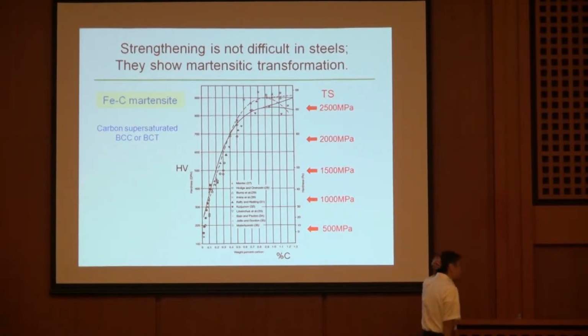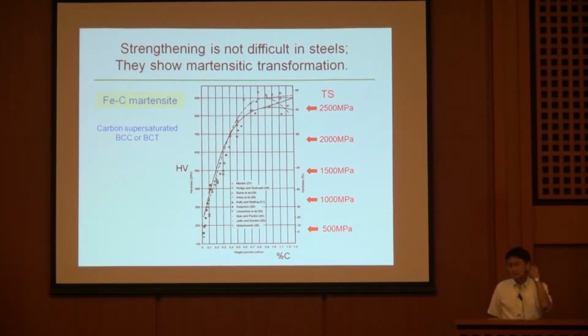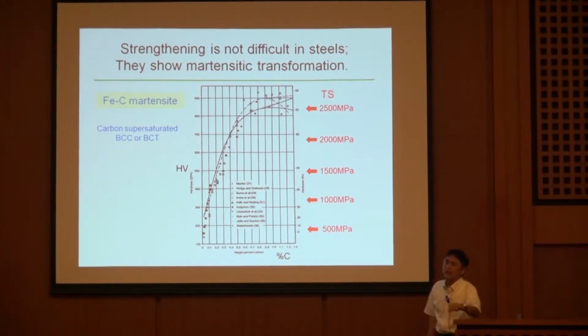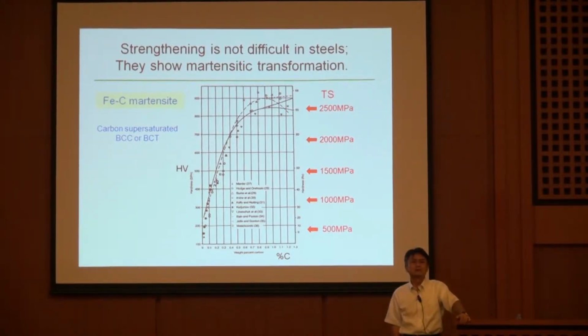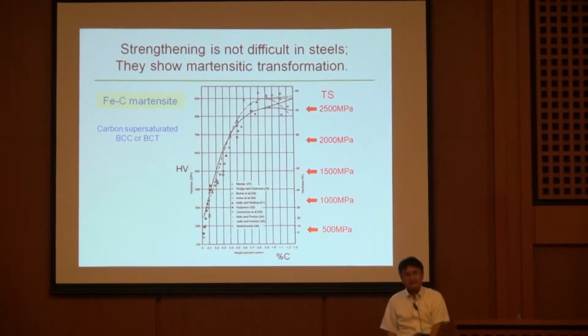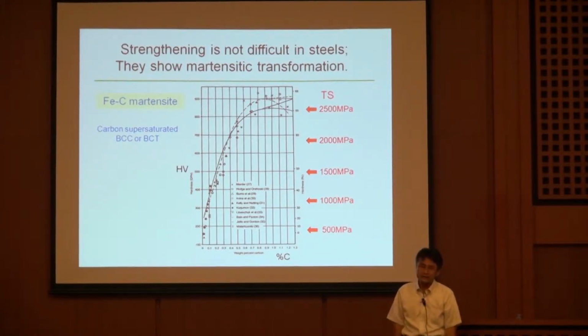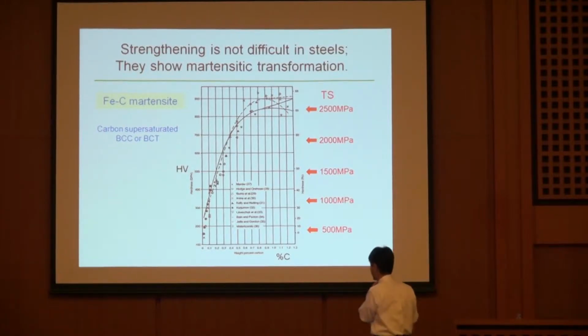So if you want to get a stronger steel, please do quenching after heating at around 1000 degrees centigrade. Then you can get the 2 gigapascal if your carbon concentration is about 0.4 mass percent.